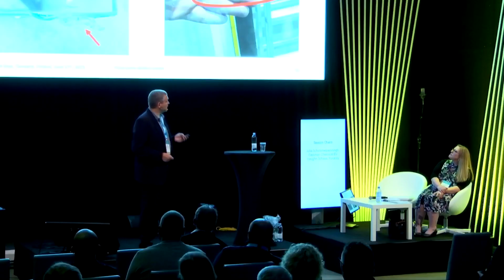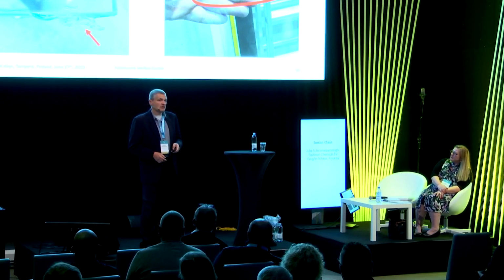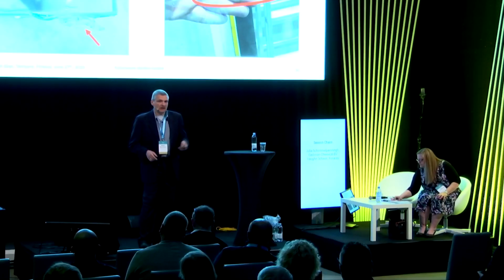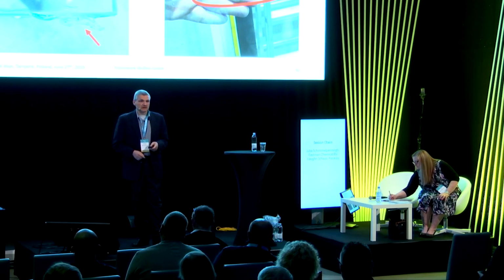Another failure we have seen happens if you run the autoclave with the standard program as you know it from PVB. EVA is a little bit sensitive, therefore we need a changed process if we want to eliminate the kind of bubble lines that you can see on one edge or at the end of the glass.